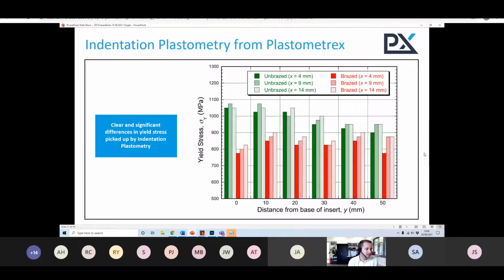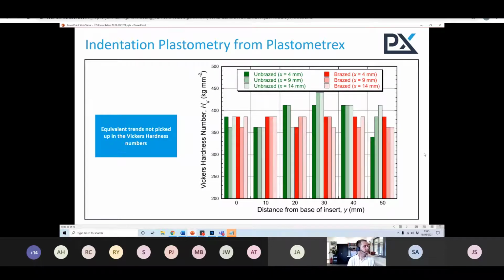Okay. Now, to finish this off, I want to show something else, which is the corresponding hardness data. So same materials, same brazing processes, same locations for the indents, but this is hardness numbers, Vickers hardness numbers actually, instead of strength characteristics. And what you see here is that the picture is more ambiguous than it was with the yield stress, less clear about what's happened. And in fact, from the data that you can see here, it would almost look as if there'd been no real consistent change in the strength of the material or the hardness of the material. And it's because the hardness numbers, as I mentioned before, can be really quite ambiguous and quite insensitive to differences in stress strain curves. And we showed an example of two very different stress strain behaviors giving very similar hardness numbers in the previous slide.